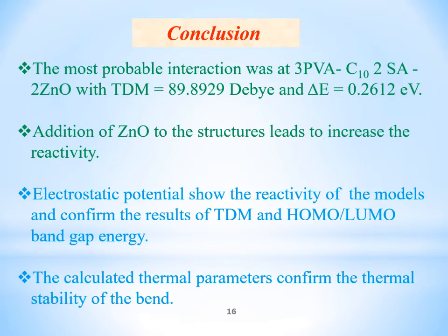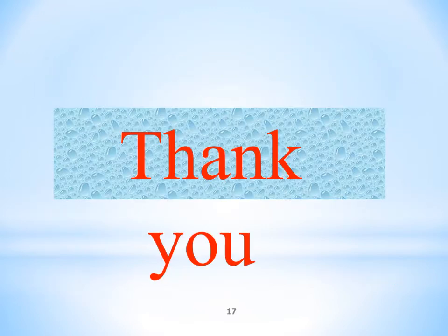By comparing the total dipole moment of the PVA sodium alginate blend and after addition of zinc oxide to the blend, the electrostatic potential shows the reactivity of the models and confirms the results of total dipole moment, HOMO and LUMO energy. Also, the calculated thermal parameters confirm the thermal stability of the blend and confirm the results of total dipole moment, HOMO and LUMO energy. Thank you very much.